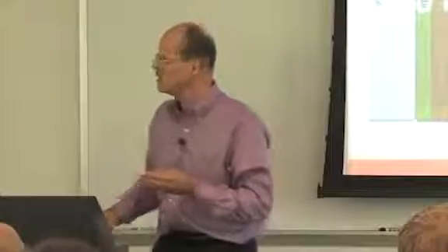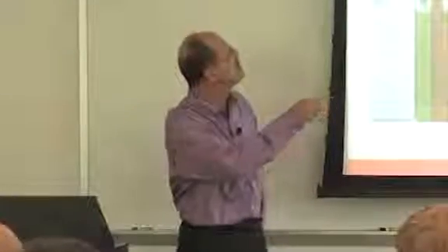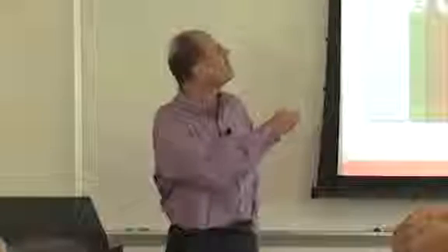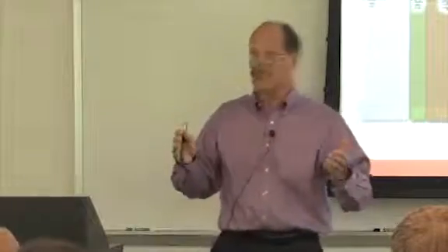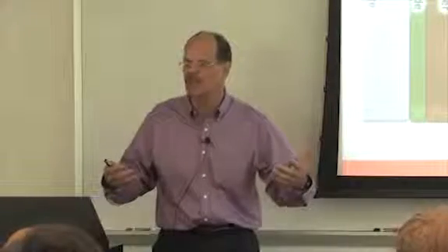The first part of your talk is right. So I have a photon absorption. I need to create charges, and I need to transport charges. And in these three things, I think it tells you already that almost everything matters. There's one component where this schematic may be misleading: I need enough percolation between these domains. Otherwise, I can split the exciton and get free charges, but I can't get them to the electrodes. So the connectivity and the percolation of the charge transport network is also important.